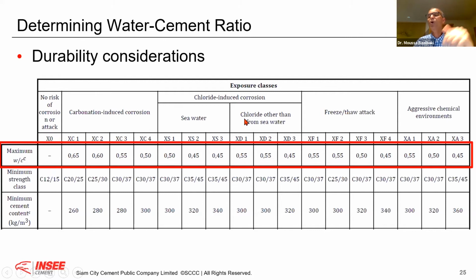Normally, we should never go above that. Because as soon as you are above 0.65, you have a problem with percolated porosity. Your porosity is percolated. I can produce a 25 megapascal, dense, good permeability, another 25 megapascal, very permeable. Therefore, that is exactly what we should keep in mind. This is why those tables exist. It's not prescriptive only. It's not on compressive strength only.